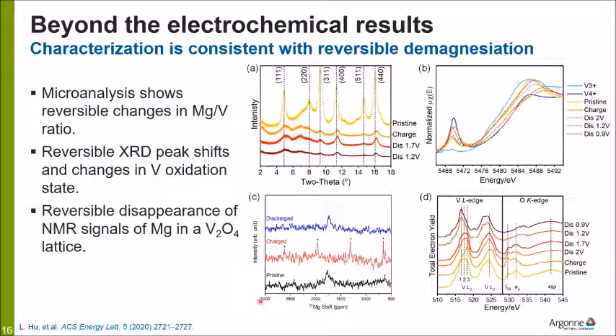The NMR was done, as I said earlier, we already discussed. And you can see that this peak here does reversibly disappear in the pristine material during the charged state, and then reappears during the discharge state. It's a little more challenging to see than in the earlier work, just due to the material type and amount that we had, but it certainly is fairly clearly obvious.